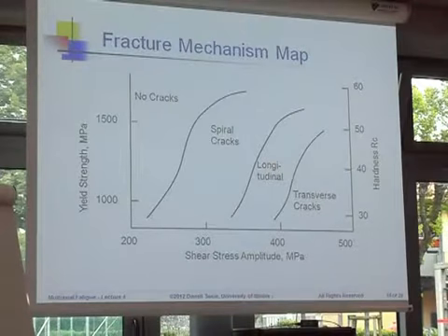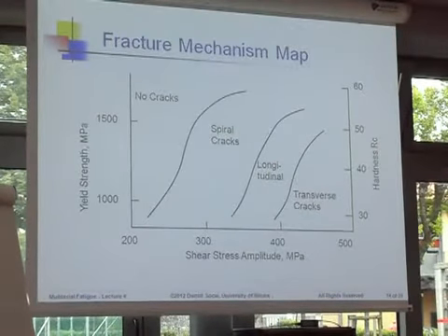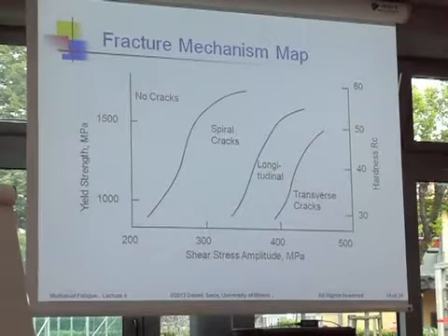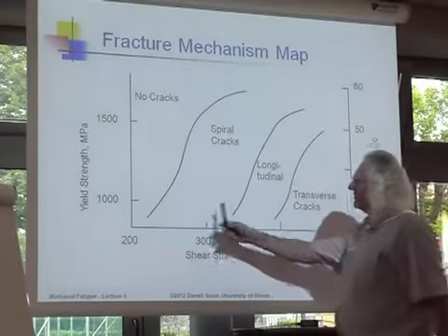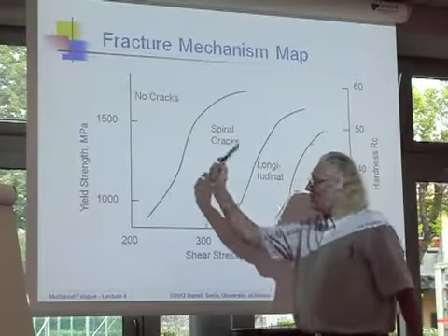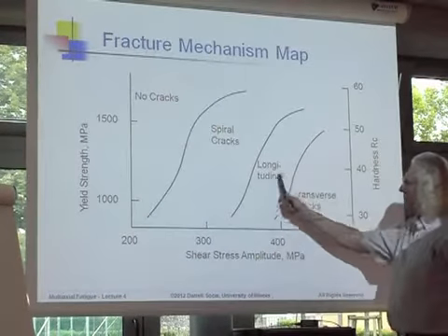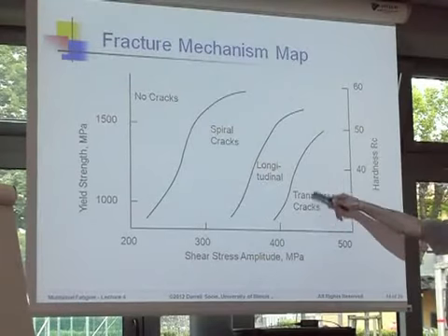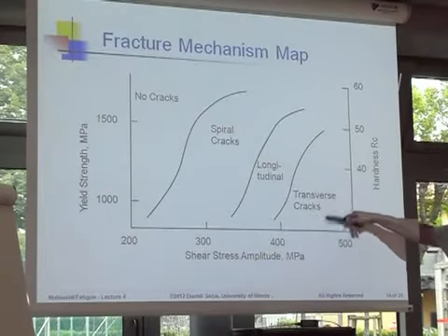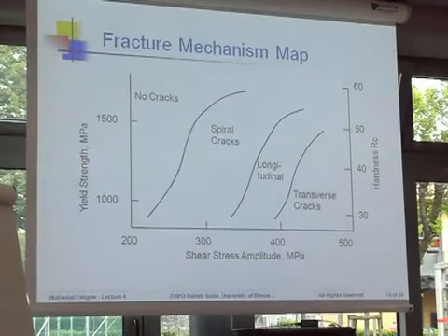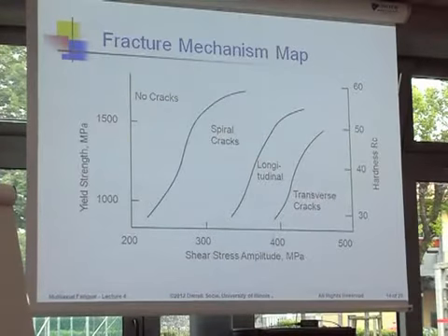It's also a function of material, and of course most of the data is in steel. This just quantifies what I just said. If you test at a low enough amplitude, of course you never get cracks. It's a long life, these spiral cracks, these longitudinal cracks, and then finally the transverse cracks at really high stresses and short lives. So that's what we observe.